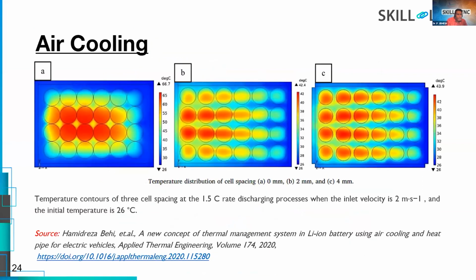And this is also one of the case studies where the space between the batteries is changed. Here you can see there are 3 cases: in the first there is no space between the batteries. In the second, case B, the space between the batteries was maintained at 2 mm, and the third one, case C, has 4 mm spacing. If you compare B and C, even though the spacing between the batteries is high in the third case, you can see a lot of hot points. So you have to optimize the distance between the batteries. You cannot just increase the battery spacing, and also you cannot maintain a close contact structure.